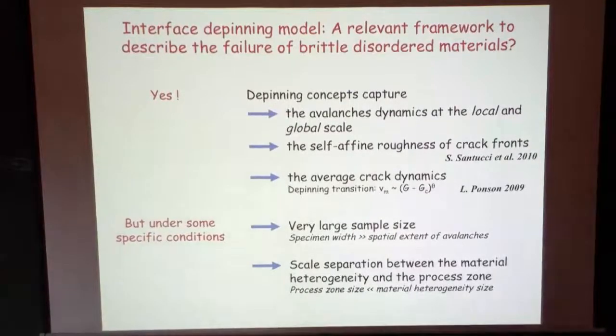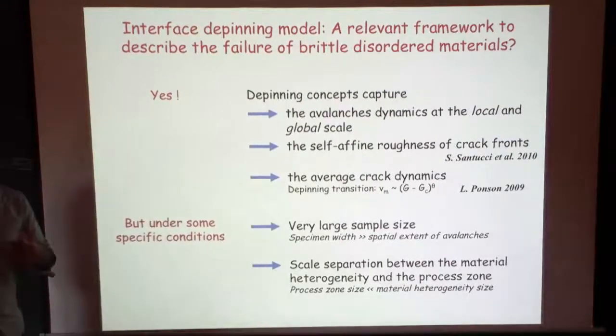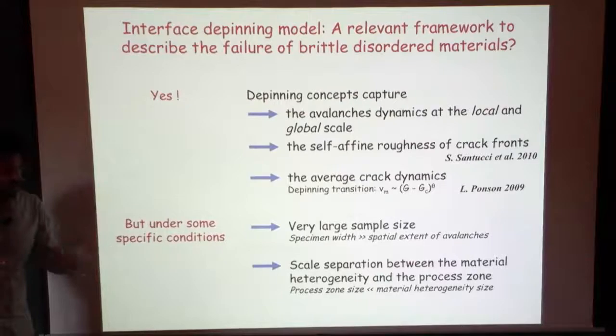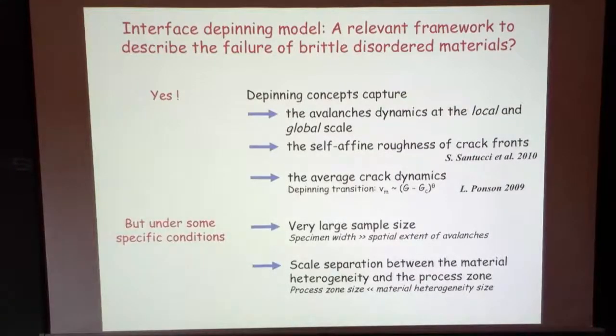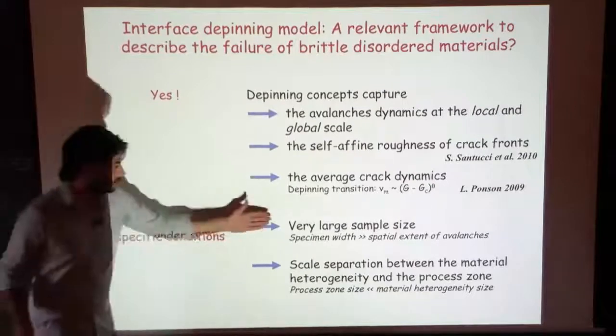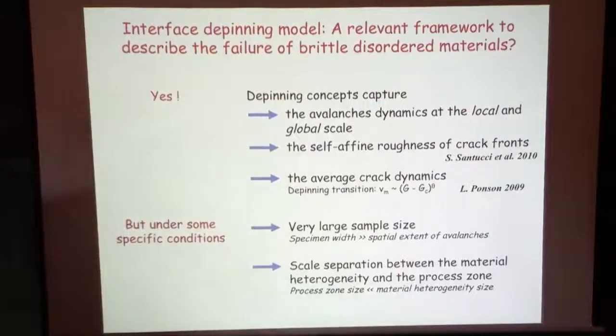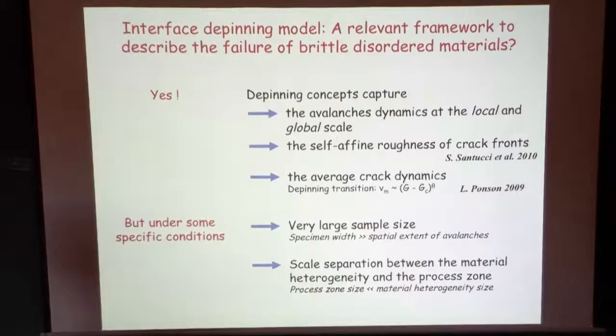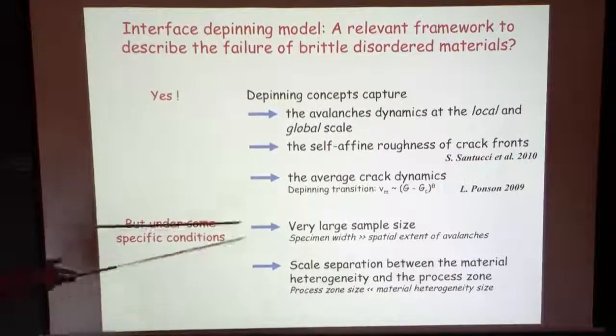Then you really need an infinite, very large system. This is due to the fact that if you want your kernel of elastic interaction to remain the one we have set up, you really need avalanche sizes, front perturbations, characterized by a length scale that is much smaller than the sample size. And this is really a big restriction that has not been respected in many experiments in the 90s at the beginning, where it was difficult to rationalize observations, and that is still a big problem.